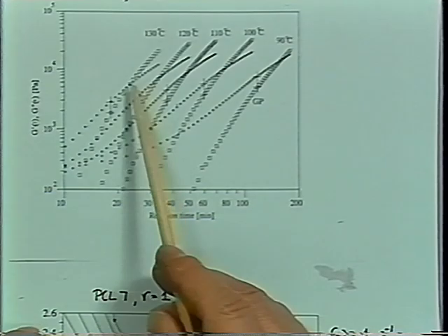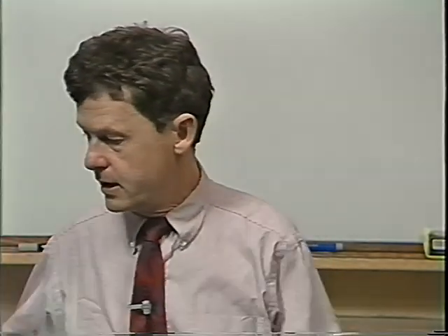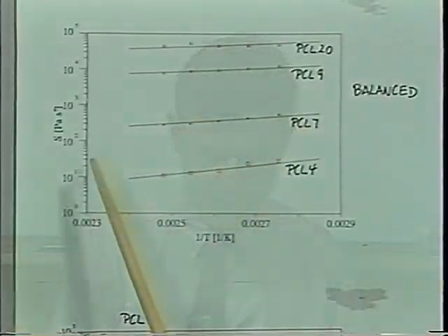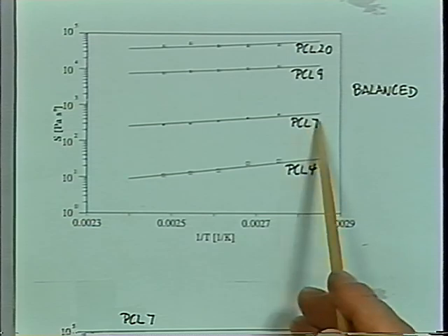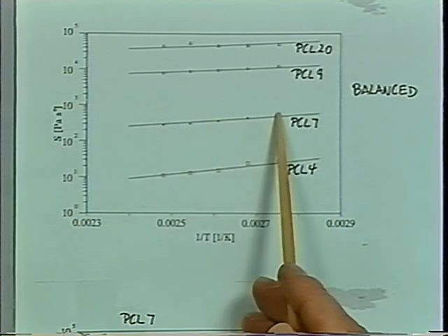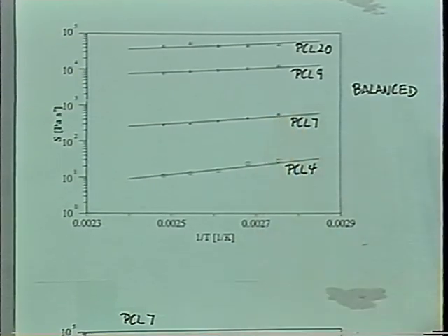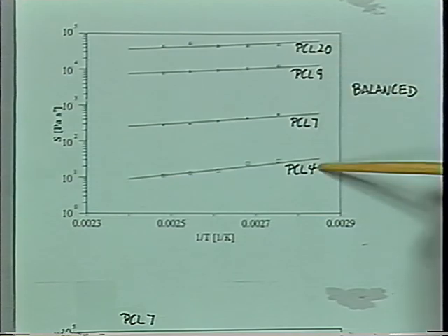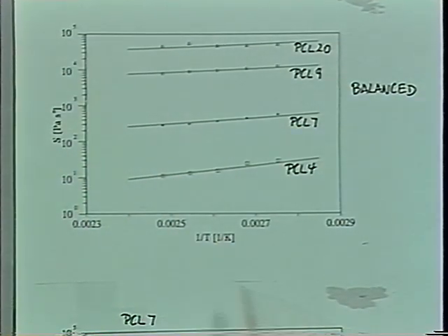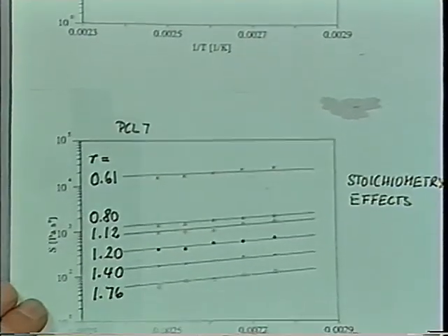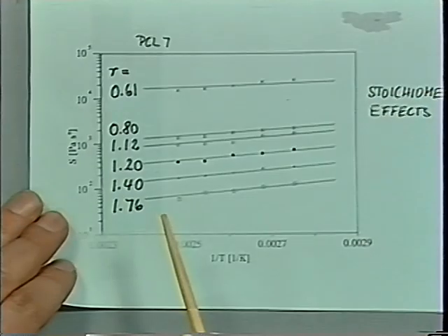And note, the gel point is not coinciding with the crossover of G prime, G double prime. Because it's occurring at some other time. But with that assumption, he knew where the gel point was, and he formed then G prime, G double prime at the gel point for those different temperatures, and for different samples. Then he got S. See, this was all for the 7,000 molecular weight. He got S now at different temperatures from the set of curves which I just showed you. He repeated that for all 4 samples and got S as a function of temperature. He plotted as 1 over the temperature. And he also did it for the 7,000 molecular weight at different stoichiometry.